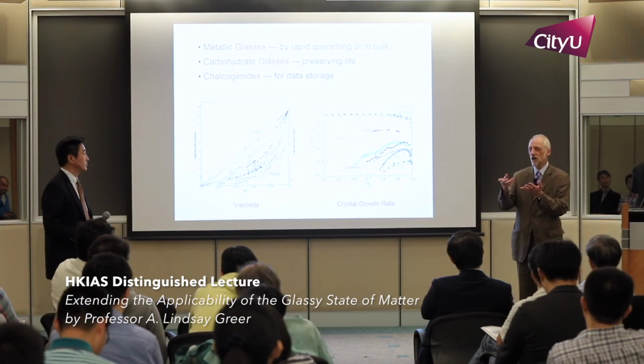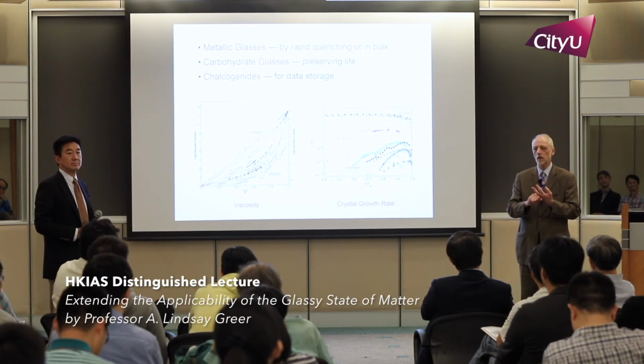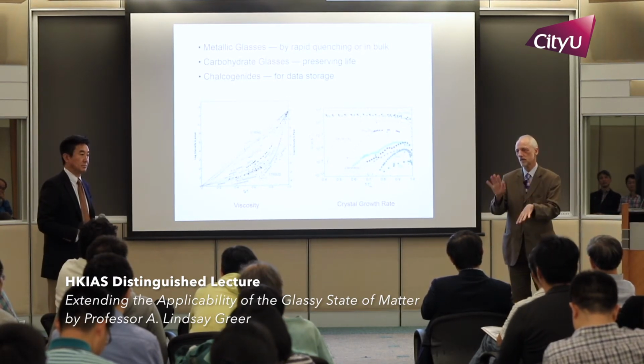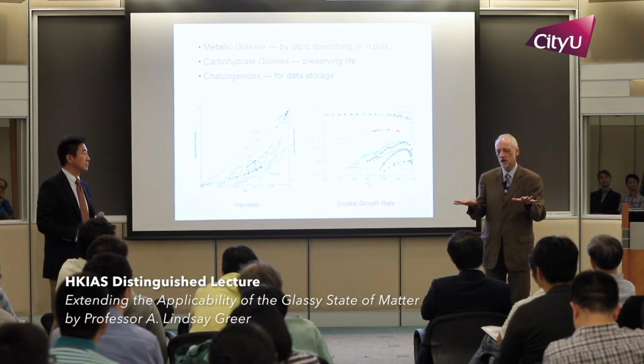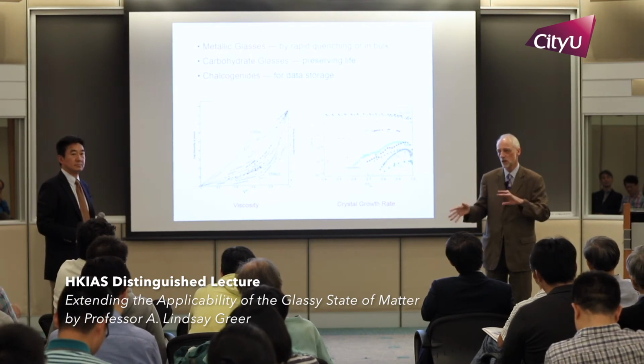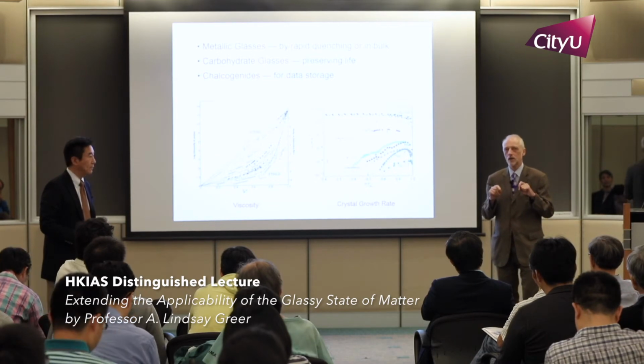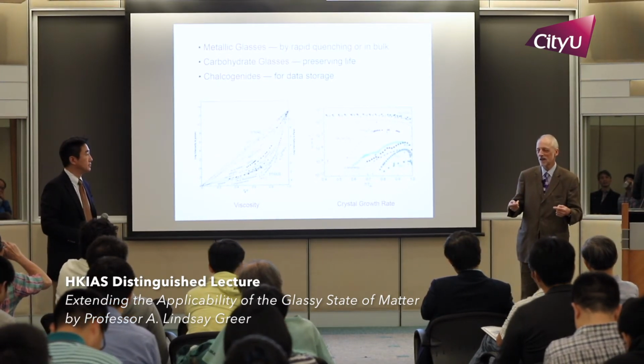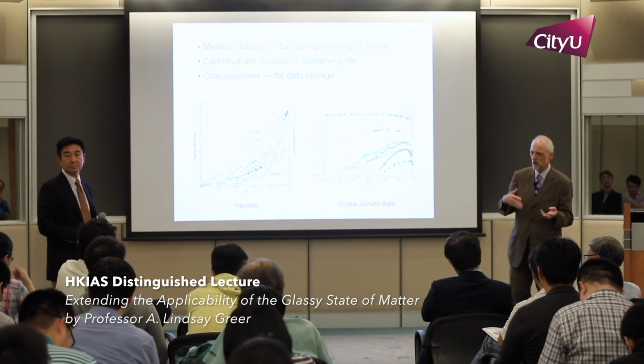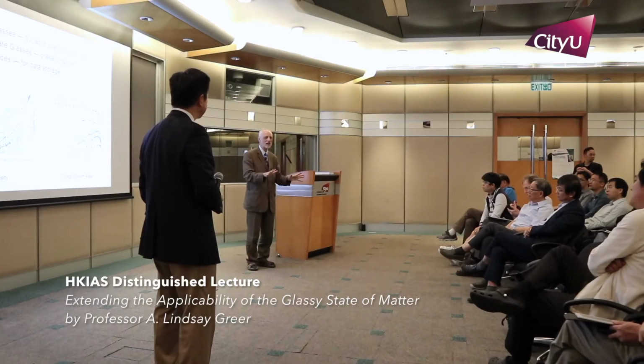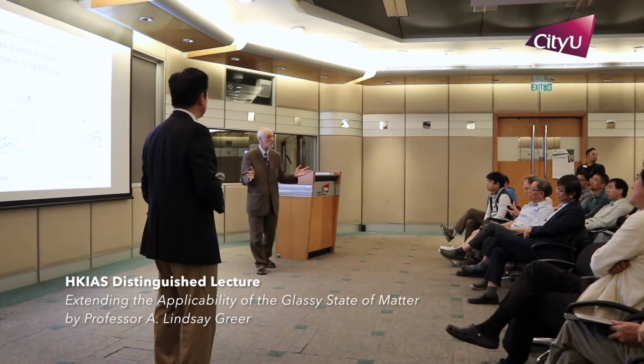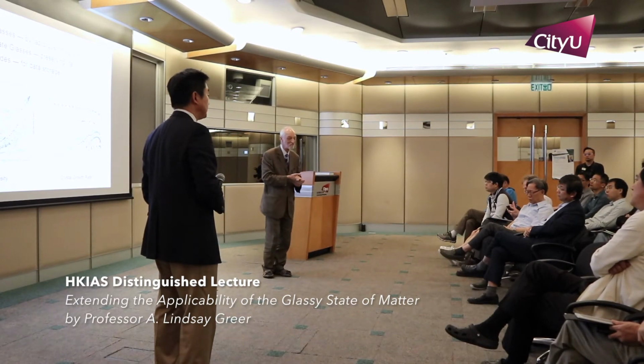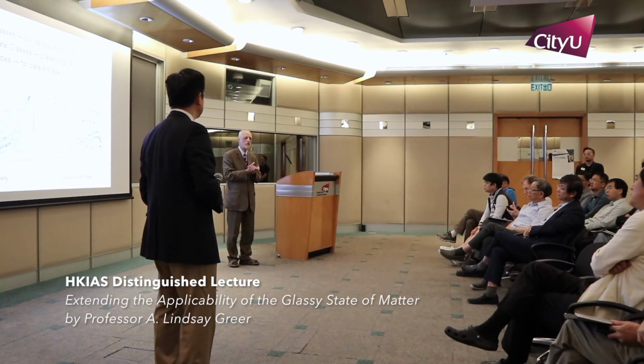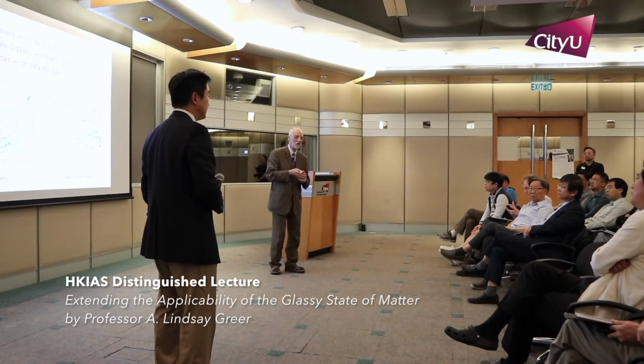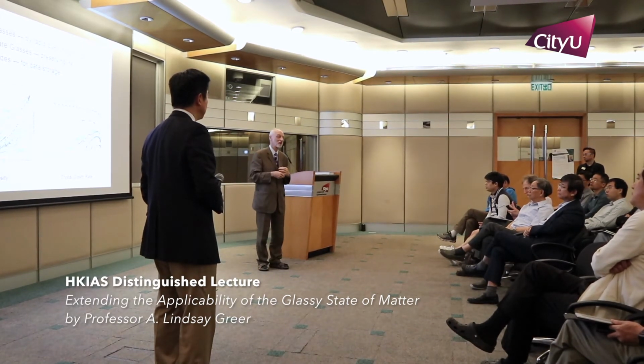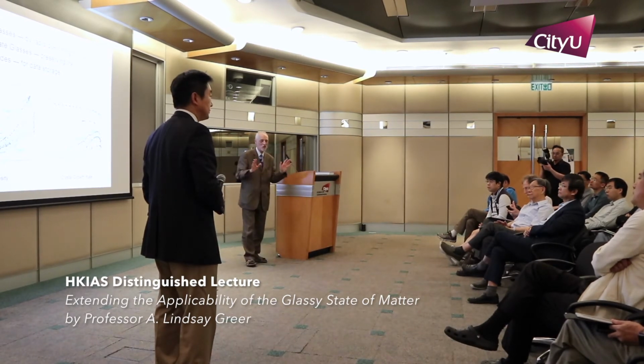We could talk oxidation, which you might think of as dry corrosion or wet corrosion. The glasses are uniform in chemistry, so you don't get your electrochemical couples so easily. So there are lots of reasons why you could expect superior resistance to corrosion of any kind. And that's further made the case that you can put alloying elements in to higher levels than you would in a crystalline system, like, say, chromium and phosphorus into an iron-based system, so they become exceedingly corrosion resistant. But they don't have to be. You can have compositions that will corrode very readily or oxidize very readily. So they can be superb, but if you try hard enough, you can make them really bad at oxidation resistance as well. So a classical copper zirconium glass, the zirconium will oxidize very readily and leave you with little copper stuff on the surface. So it's a complete spectrum.